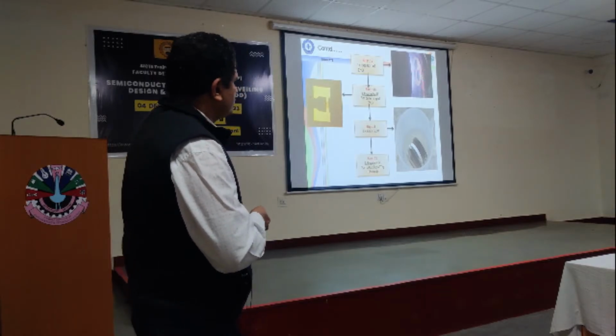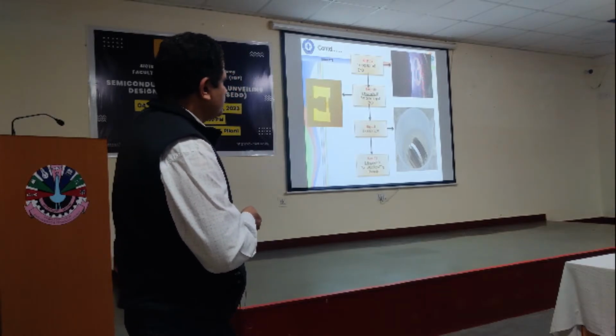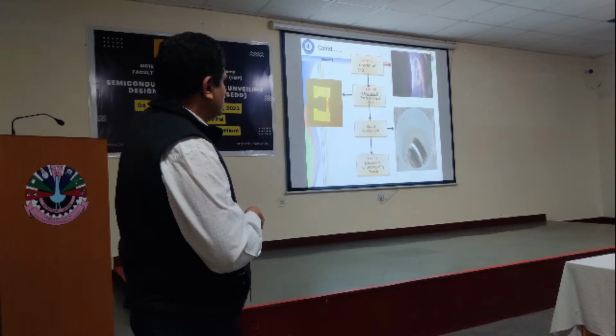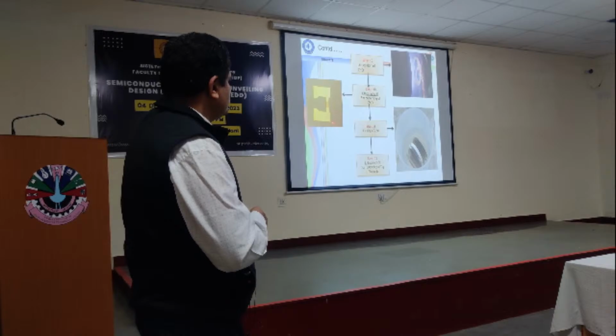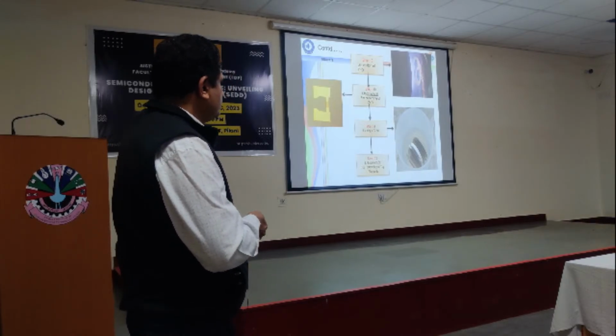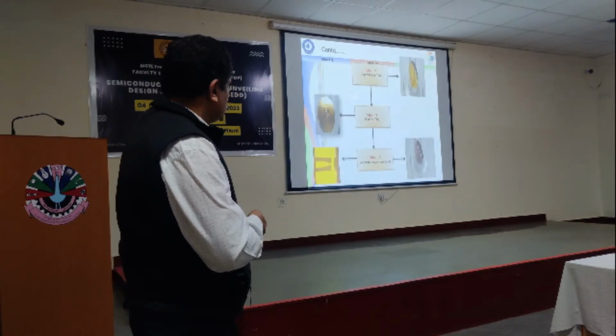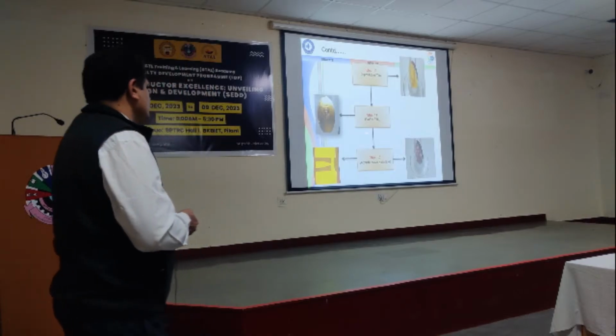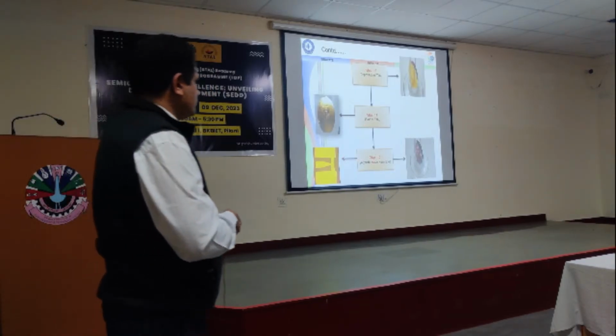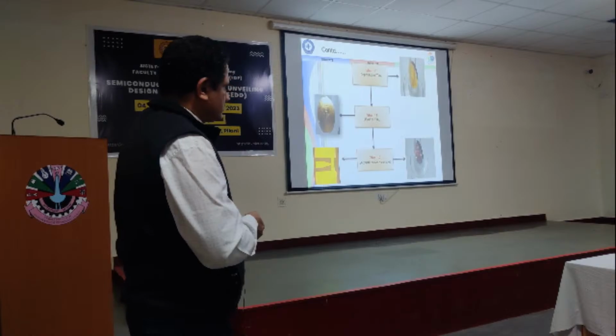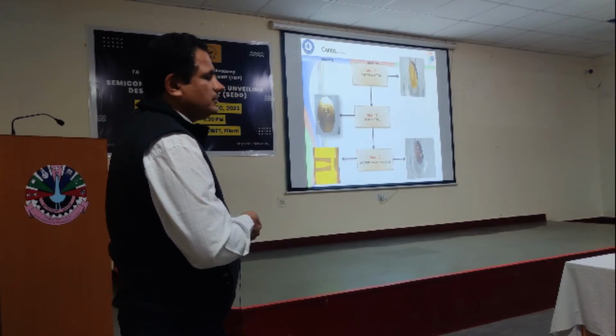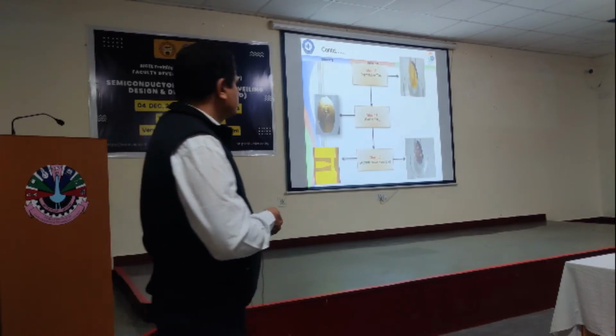Then you see the zinc oxide deposition. 3-inch wafers at a time we can deposit. And you can see the plasma color. Then the lithography is done, zinc oxide patterning, zinc oxide etching. We do 6 wafers in a batch. Then the deposition of titanium gold, then the lift-off process, and the resonator is ready on these wafers. And finally, we do wafer-level testing.